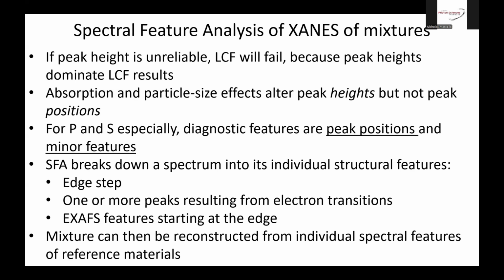Absorption and particle size effects alter the peak heights, but they don't change the position. That's the key. For phosphorus and sulfur especially, at lower energy edges, the diagnostic features are the peak position and smaller minor features. Those are the diagnostic features, so you should concentrate on them and not worry so much about the peak height. So SFA breaks down a spectrum into its individual structural features. You dismantle a XANES spectrum into the edge step itself, one or more peaks resulting from electron transitions, and the start of the XAFS oscillations. So if you break down your reference standards in the same way, then you can reassemble those components into fitting for your unknown mixture and be independent of peak height issues.